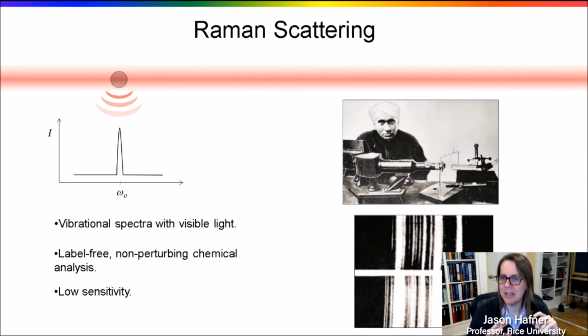That beam is a laser beam going to the right. The gray circle is like a dielectric sphere or a gold sphere, what do you want to call it? Just a particle that's going to scatter the light. And it scatters the light away. And what is the color or frequency of the scattered light? No, it's the same as the laser. Why would it be different? So the laser causes the electrons to jiggle at the frequency of the laser. That jiggling radiates light, so it's the same frequency. So that plot is like as though we had taken a frequency spectrum of the scattered light. And you can see it's just a peak at omega naught, which I'm saying was the frequency of the laser.